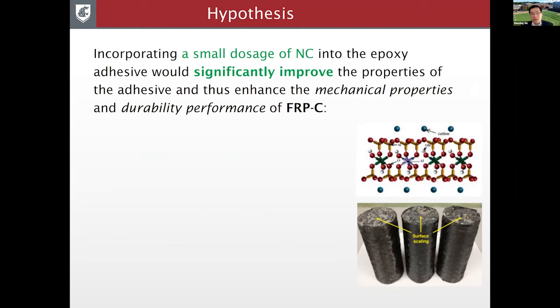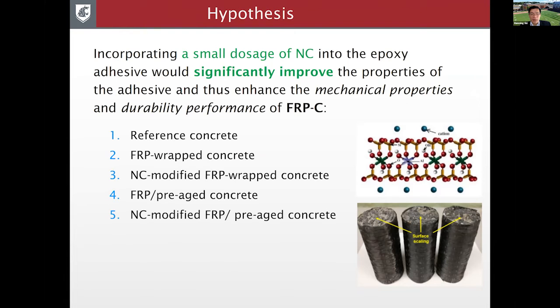So our hypothesis is that by incorporating a small dosage of nanoclay into the epoxy adhesive, that would significantly improve the properties of the adhesive and therefore enhance the mechanical properties and durability performance of the externally bonded FRP to concrete.